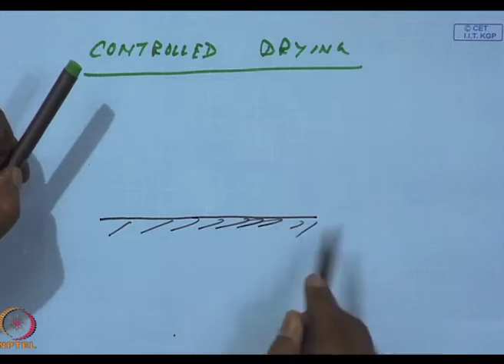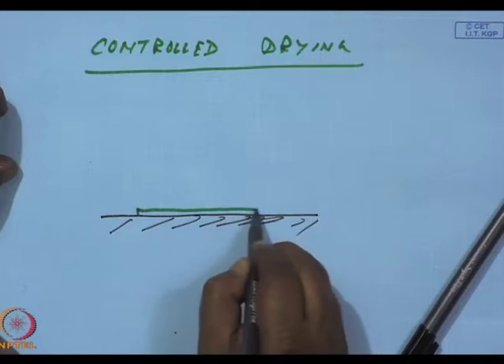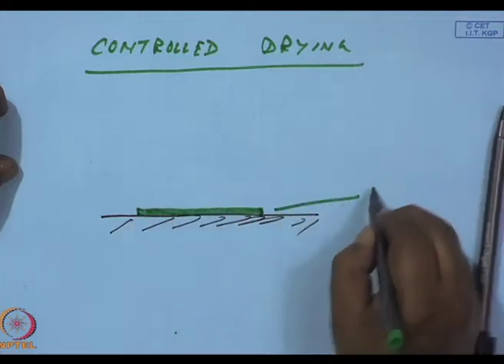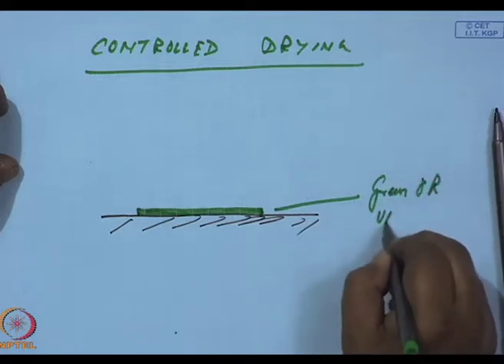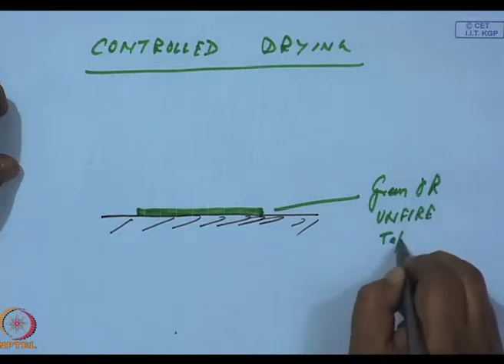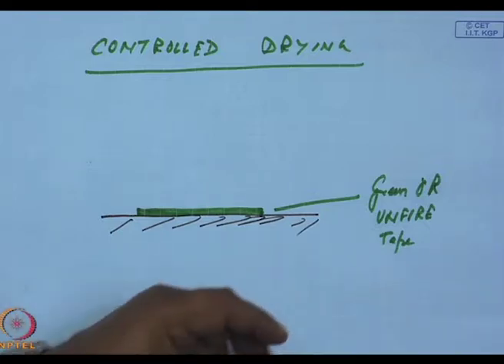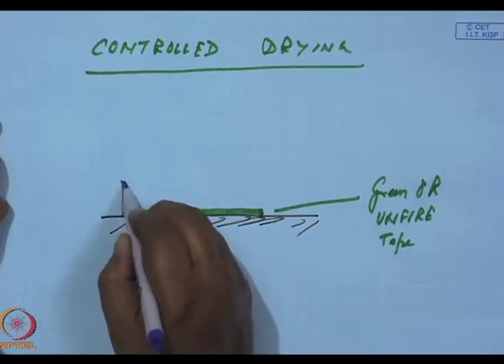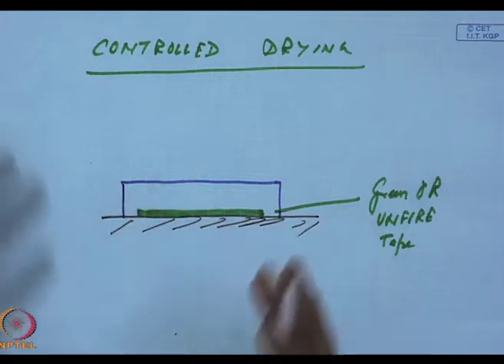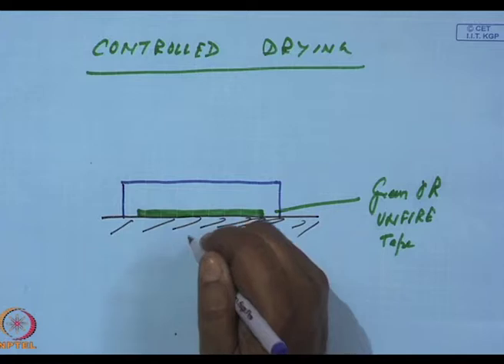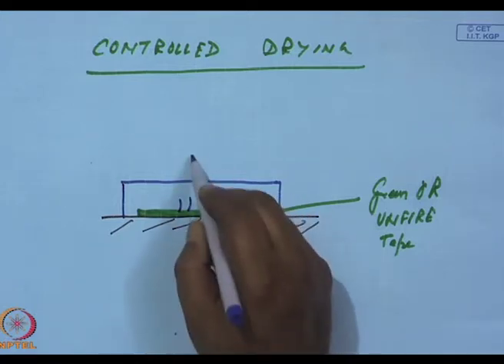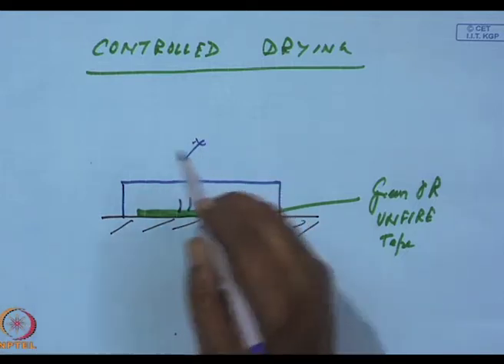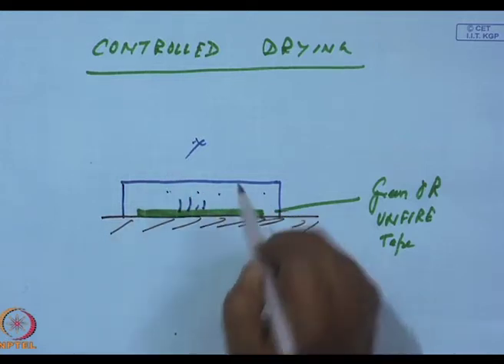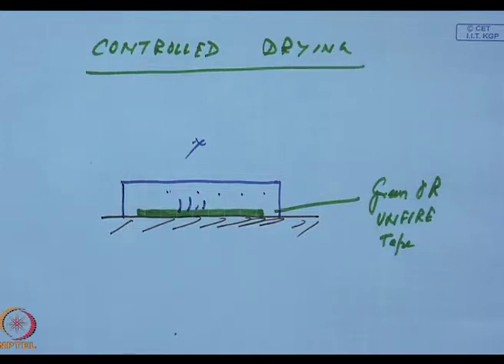If this is the platen, if this is a green tape, green or unfired tape, what I would do is cover it up with a glass or whatever sized vessel, so that the vapors which went off did not get lost in atmosphere. As the vapors went off from the surface, the gas phase here got richer in the solvent, and as evaporation proceeded, the gas phase would get richer and richer, and the rate of evaporation would drop.